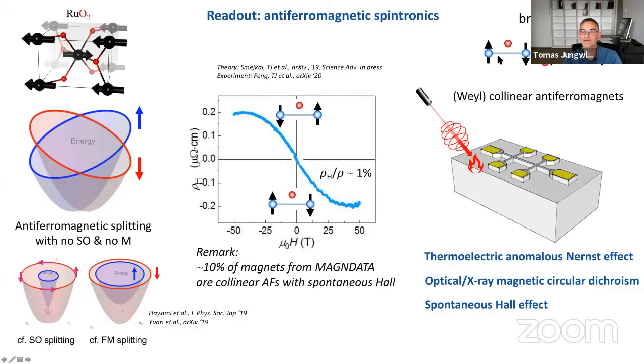So if you have a crystal which has this type of broken symmetry, and there is an example of ruthenium dioxide, which is a member of a very broad family of collinear antiferromagnets, this in principle allows for the anomalous Hall effect. Now, this is not only a theoretical prediction, but it has also been experimentally verified recently in this ruthenium dioxide that you can have the anomalous Hall effect.